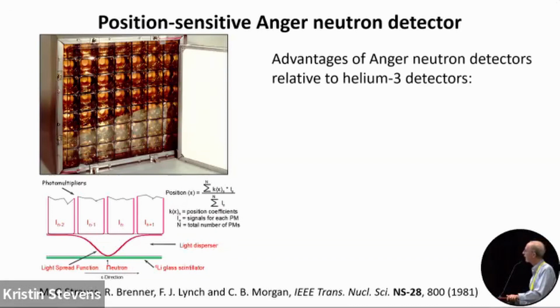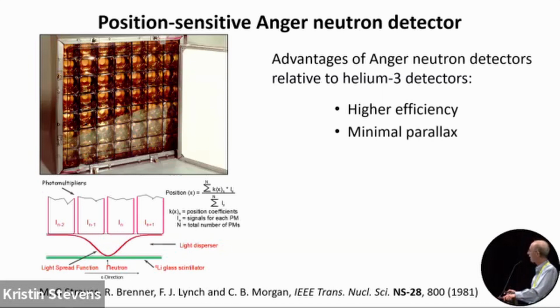So the advantages of the Anger neutron detectors relative to helium-3 detectors include higher efficiency, a lot more lithium-6 in even a little bit of scintillator glass versus a couple atmospheres in a gas-filled detector. Minimal parallax, the scintillator material is only around 2 millimeters thick down here. And this is a scintillator glass, which would sit in front of the photomultiplier tubes.